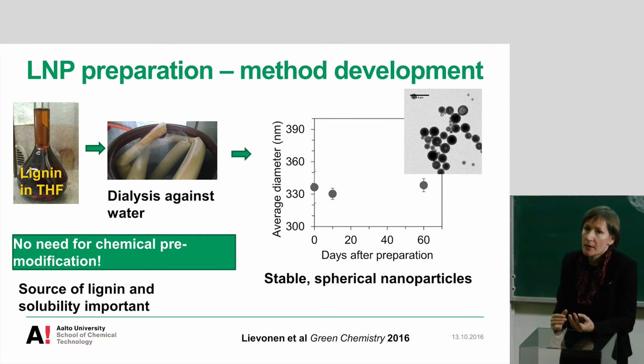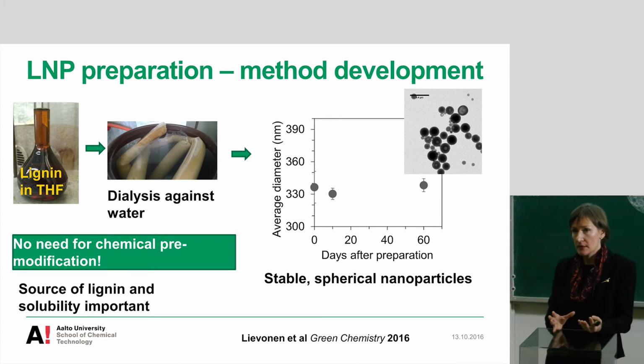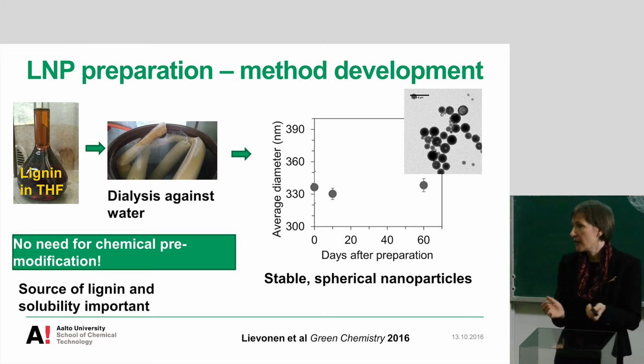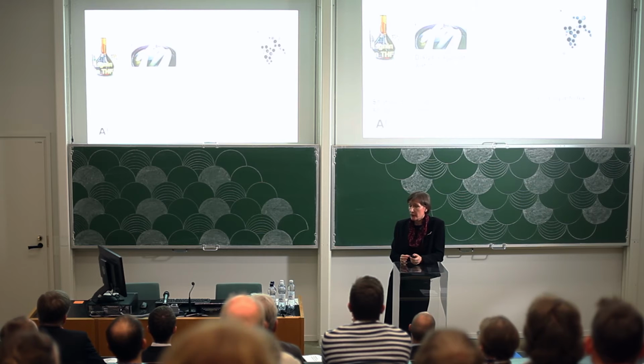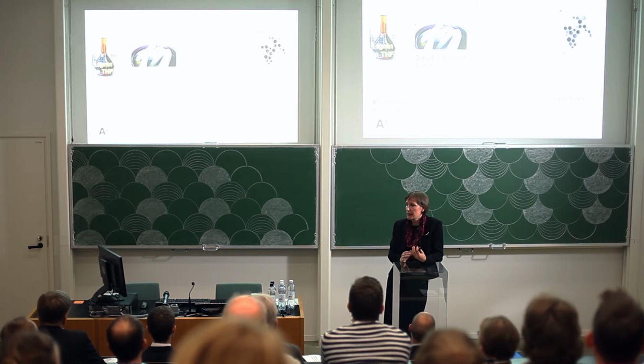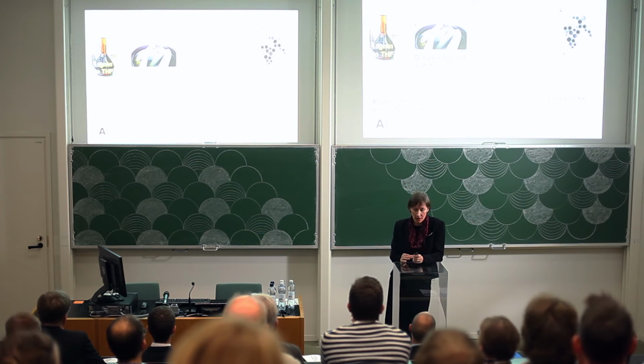And we did this by dissolving lignin into an organic solvent, tetrahydrofuran in this case, and then we added a non-solvent, pure water. And when the lignin comes into this non-solvent, it spontaneously self-assembles into spherical particles. And they are very stable. And what's very neat with our finding was that we didn't need any chemical pre-modification of the lignin to be able to make these nanoparticles.